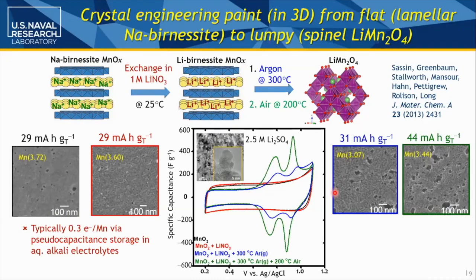But if you give it a little bit of air at a lower temperature, so you're not oxidizing the carbon, you crystallize that paint that was originally layered into a lithium spinel. And now you've got the beautiful battery response you'd expect for an intercalating system. And the reason Megan and Jeff were really focused on this is putting a lot more charge in the positive end of the spectrum. They would then pair this system with a rust-painted carbon fiber paper and have a doubly asymmetric electrochemical capacitor. And that can give you approaching 2 volts in an aqueous system, because both electrodes are suppressing either water oxidation or water reduction.